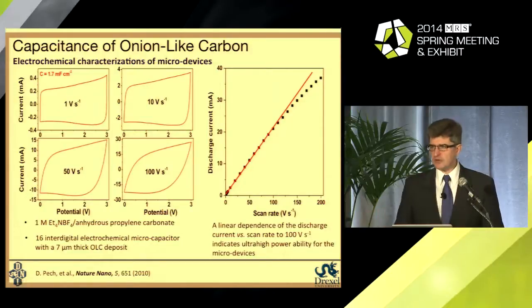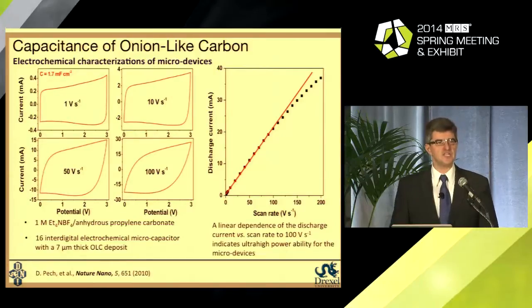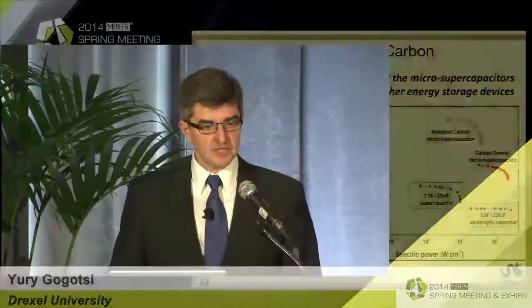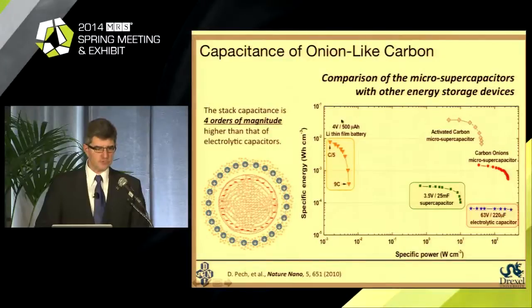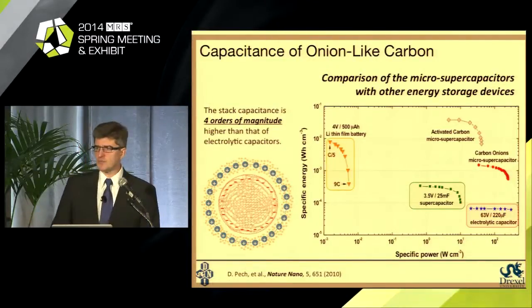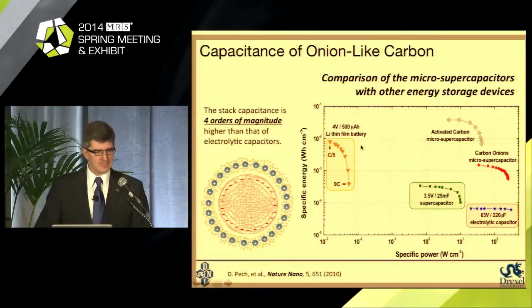So imagine it takes you about an hour to charge your computer battery, or a couple of hours usually to charge a phone battery here. Here, if your device is 3 volt, 2.7 volt, usually supercapacitors with organic electrolyte, you can charge them in tens or hundreds of milliseconds here. So it shows how by changing the structure of carbon, we can go from seconds, tens of seconds charge for activated porous carbons to millisecond charges of the material here. And of course, in this case, we can already move on to a plot, and actually this is a Ragone plot somewhat similar to the one I showed you before, comparing simply thin film lithium-ion batteries, supercapacitors, electrolytic capacitors here. What is interesting, you will see.